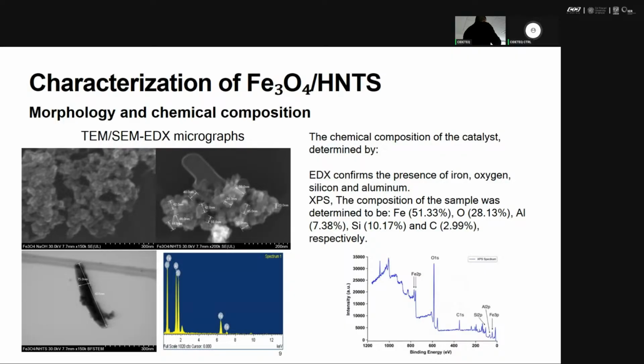For that reason, I use the halloysite, because it is a support of nanotubes. Here is the halloysite, and here is the magnetite, which is used because it avoids agglomeration. And then I analyzed by EDS to confirm the presence of iron, oxygen, silicon, aluminum, and by XPS to analyze the composition, to be sure that all the materials are present in the nanocomposite.